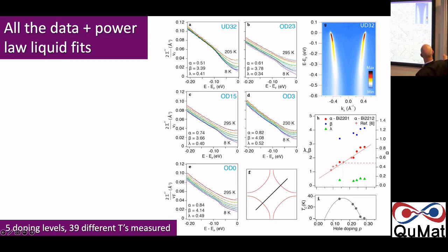And if we fit all of these data, that's the ones I've shown already, we can, for example, plot this alpha as a function of doping. So here's the superconducting phase diagram. We're looking at this part here, the overdoped part. Colleagues in the US who developed this power law liquid formula, they were looking at the underdoped part, and it really, really suspiciously just lies exactly on top of each other. So there seems to be a linear growth in this power law. So it's omega squared plus T squared to the power alpha. And alpha at optimal doping is exactly 0.5.